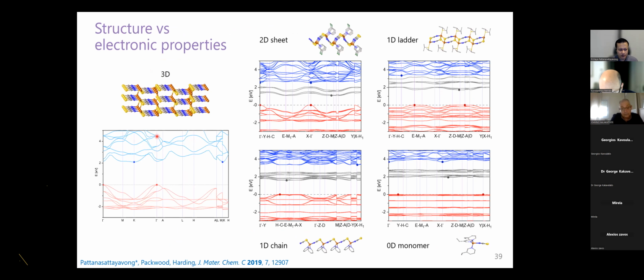So we look at the electronic structures. This is actually as expected. When we cut down the dimensionality from the three-dimensional state, the key hole transport pathway is through the copper and sulfur. This forms extended two-dimensional layers, as I mentioned earlier. When we cut the structure down to 2D, this copper and sulfur network still retains a one-dimensional substructure inside. So it still shows some dispersion, some possibility for hole transport. But if we reduce the dimensionality down further to 1D or 0D, we can see that the valence band becomes narrower and also flatter, meaning that the hole transport is now gone, basically. The properties are deteriorated.